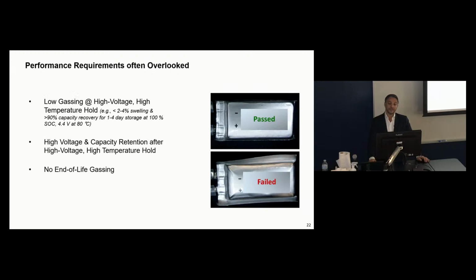In addition, when you have a safety test for the batteries, typically what you do, you charge the battery to high voltage, and you hold it at high temperature for quite some time, and then you see if the battery swells or it doesn't, and how much capacity it retains. And this test is actually cell-specific, so you have to build the proper cell in order to test it properly. And certainly in an academic environment, we cannot build high-performance large batteries.